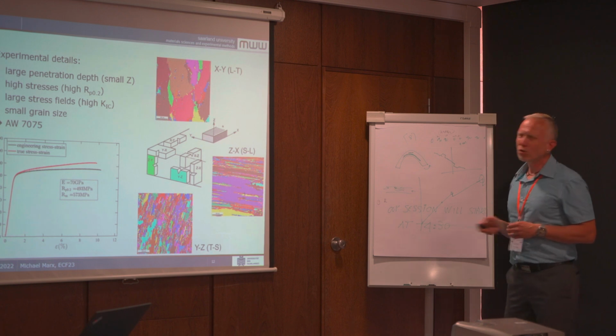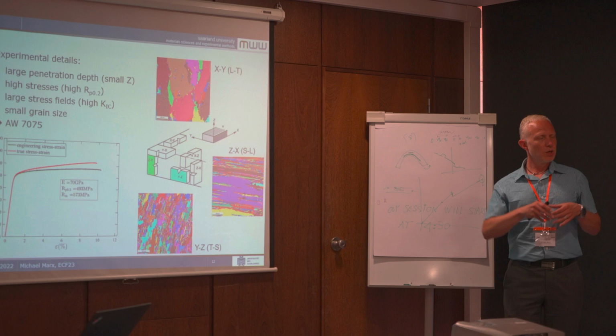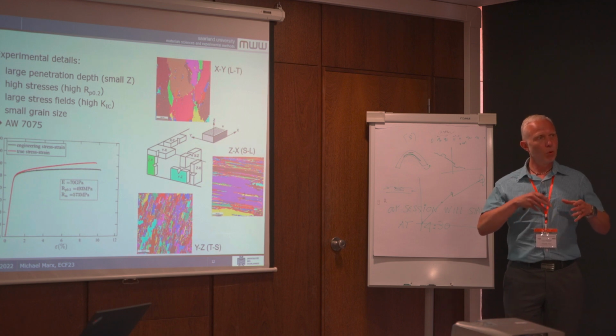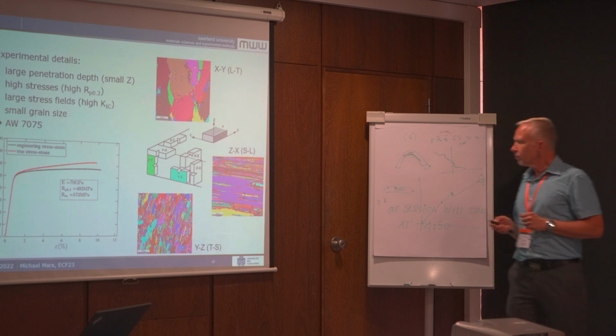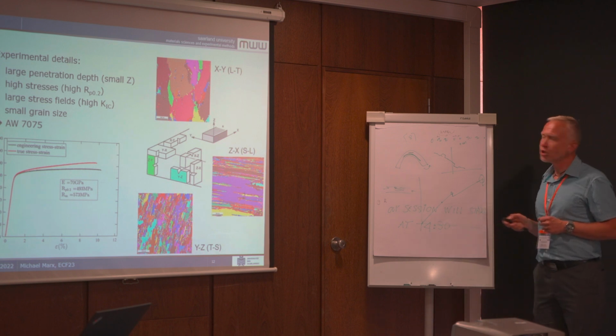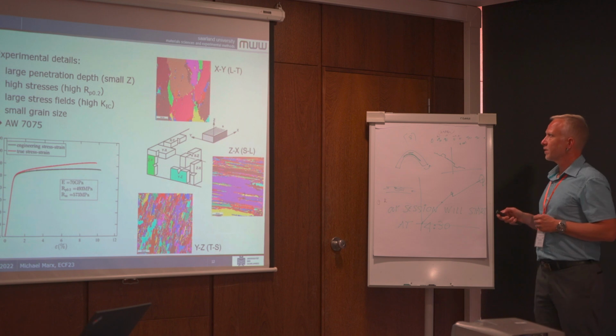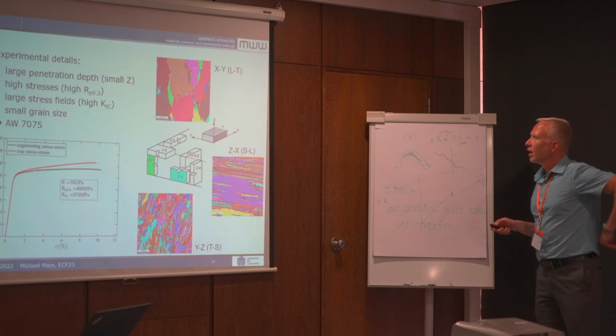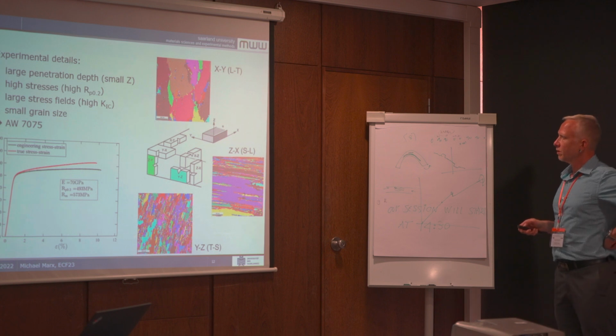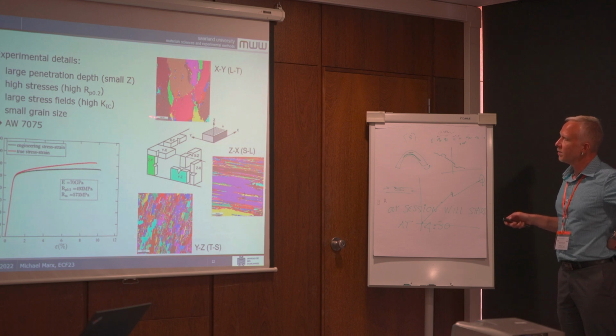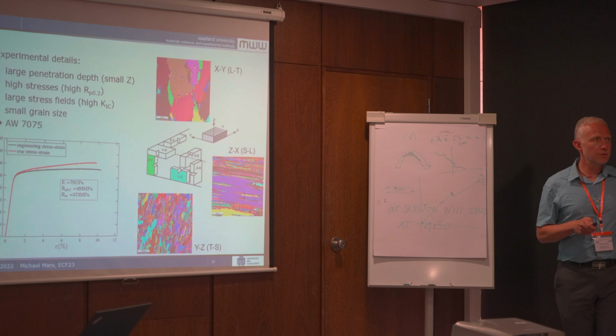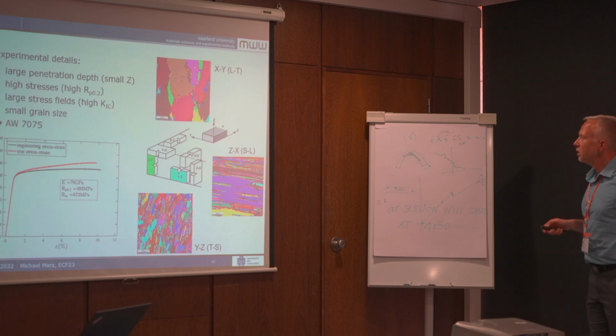And we also need a small grain size, because we need more crystals in our spot of the X-rays to not measure in a single crystal case. So here we have our plate, and there we have different textures due to the rolling process. If we look here on this surface, we have large grains. This here, 100 microns, is the spot size of our XRD.